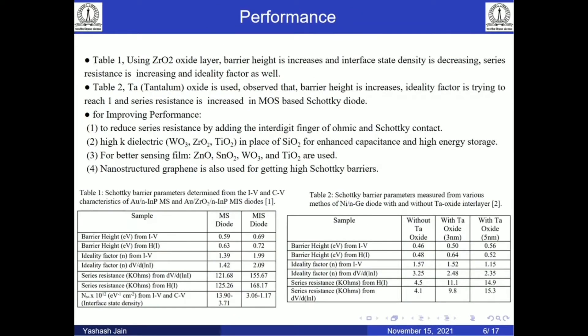Let's compare the MOS-based structure with the simple metal-semiconductor based Schottky diode structure. In Table 1 and Table 2, we found that the MOS-based device provides higher barrier heights and the ideality factor approaches unity, which is good. However, the disadvantage of this MOS-based device is higher series resistance. To solve this, researchers found that we can add interdigitated fingers of ohmic and Schottky contacts. In Table 1 we used zirconium oxide and in Table 2 we used tantalum oxide.